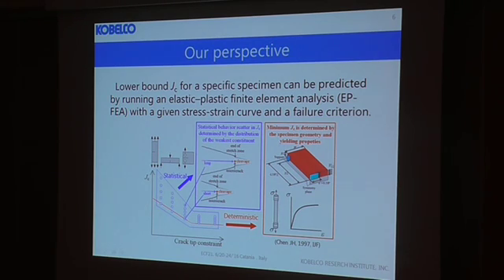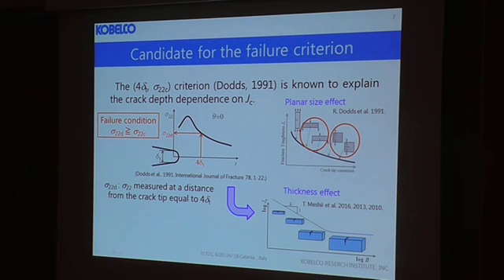We interpreted Chen's opinion as meaning that a minimum JC can be reproduced by running an elastic plastic finite element analysis, EPFEA, with a given stress strain curve and a failure criterion. For the failure criterion, we consider one of the modified Ritchie-Knott-Rice RKR failure criteria, that is the 4δT σ2C criterion, which predicts the onset of cleavage fracture when the crack opening stress σ22, measured at a distance from the crack tip equal to 4 times the crack tip opening displacement CTOD δT, hereinafter denoted as σ22D, exceeds a critical value σ2C.